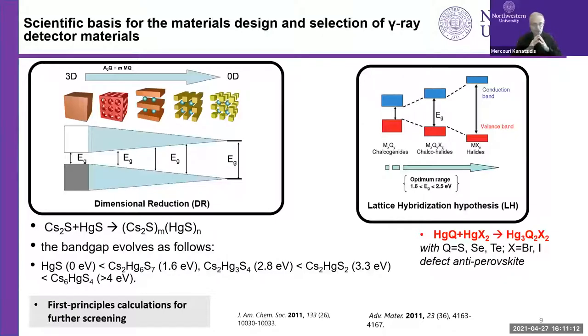On the left, we have something called dimensional reduction. We are reducing the dimensionality of the semiconductor by doing chemistry, forming new materials with lower and lower dimensionality. The idea here is if you start with a three-dimensional material that has heavy elements, so it absorbs a lot of gamma rays, but the band gap is too small, so it's useless. You can dimensionally reduce it doing chemistry and make lower dimensionality. And since these materials also have heavy elements, they will have high absorption for gamma rays, but they will have bigger band gaps. Because as you lower the dimensionality, you narrow the electronic bands and you widen the band gaps between them. And so here's an example.